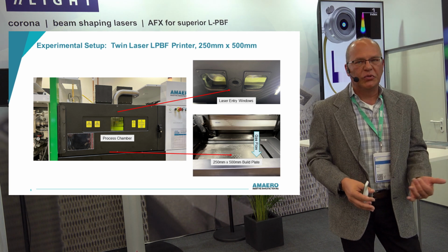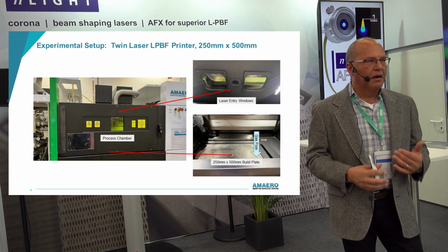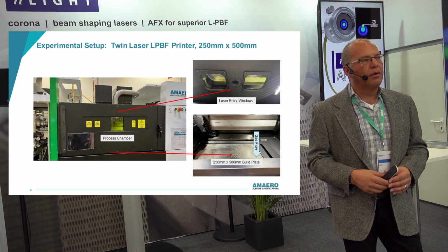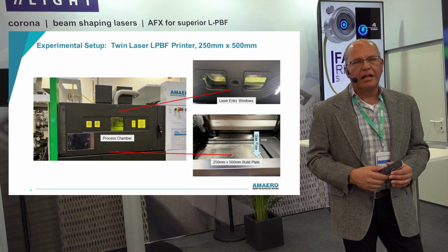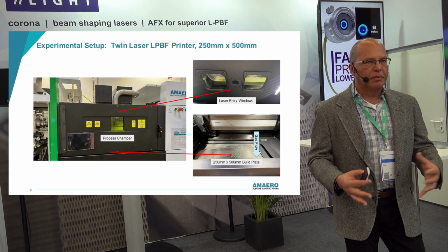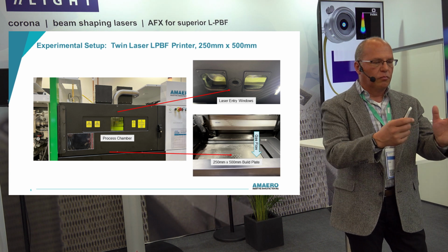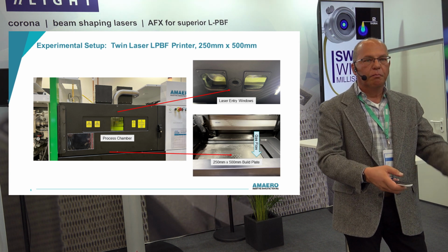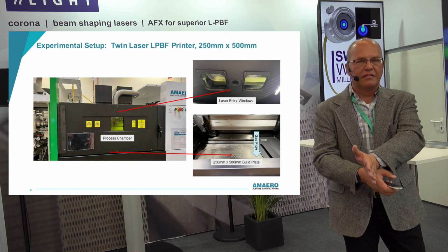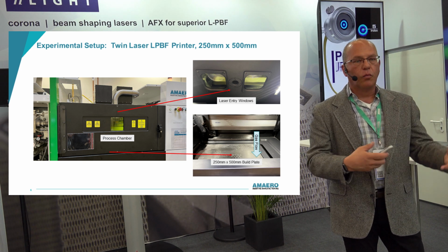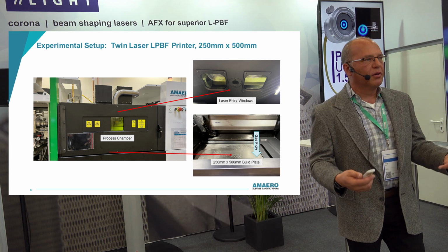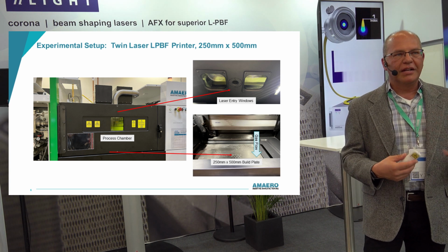It was an H-13 tool steel. Most people think that is an unprintable material because it's very crack prone, and it's crack prone because it does not like extreme thermal gradients. But think about printing. We take warm powder, convert it to boiling metal, and then back to consolidated hot metal in like 1 second. That's a very extreme thermal gradient. So how do you print H-13?